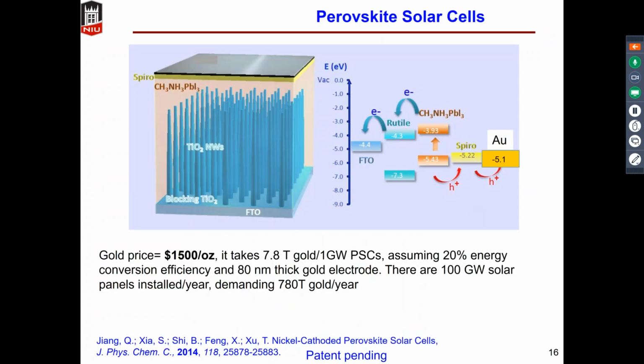So the choice of gold as the cathode would be a very costly choice, right? Especially since the gold price is around $1,500 per ounce. If you take this price and calculate, every 1 gigawatt of perovskite solar cells will have to use 7.8 tons of gold, assuming that the conversion efficiency of the perovskite module would reach 20%, and we only need an 80 nanometer thick gold electrode.